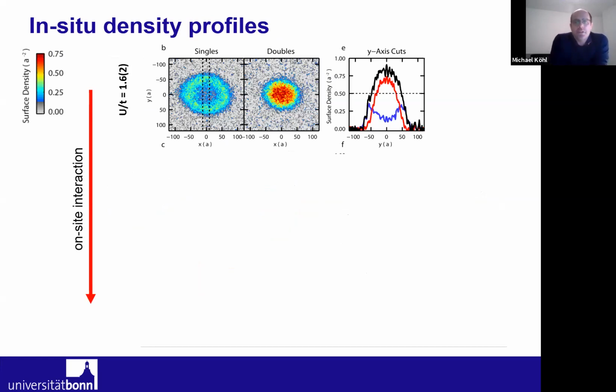Here's a sample of pictures from this experiment. And what we can do in our setup is, for each and every realization of our quantum gas, we can take 2 observations. So we can either measure the singles occupation and the doubles occupation in the lattice, and that is shown in this example. Or we can measure the spin down density and the spin up density. And that's very important that we do this for 2 measurements for 1 realization of the experiment, because then we can really take correlation measurements between the 2 different pictures.